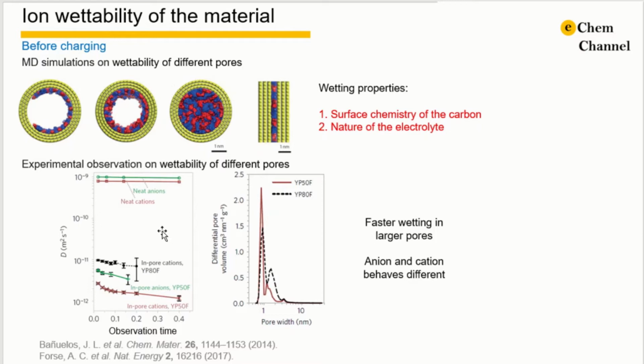For solid-state NMR, the absorption of the electrolyte into the pores will result in a clear peak shift, reflecting the confinement of the ions. Adding a very small amount of electrolyte onto the electrode material, NMR signals are observed that are shifted towards lower frequencies. It means that the electrolyte goes into the electrode material before charge.